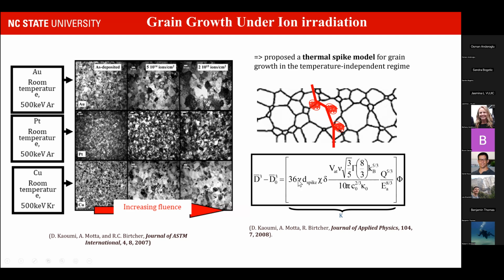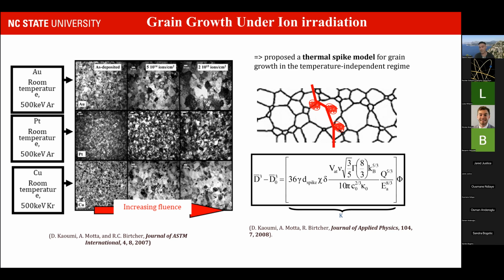And we developed an expression for K, which is very ugly, but also very satisfying, because that expression for K was dependent not only on material properties, such as the heat conductivity, the heat capacity, etc., but also on the irradiation conditions: the spike size, the point cascade size, the number of cascades per ion per unit depth, etc. If you're interested in this particular type of work, the whole derivation is in this article here.